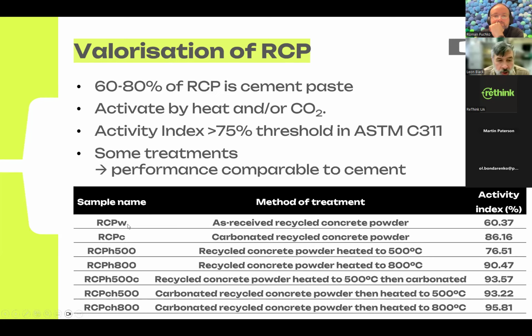What the table shows here is a range of the original material plus 6 different treatments. The as received material has activity of 60%. It's below this threshold. But all of the other treatments, either heating or carbonating, improved performance sufficiently that they could be considered as suitable cement replacements. Actually, combined carbonation followed by heating gave performance comparable to that of cement. Okay.